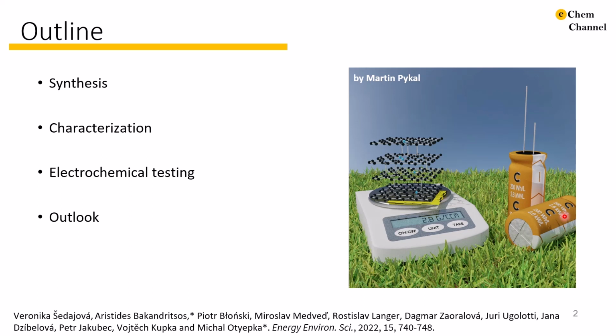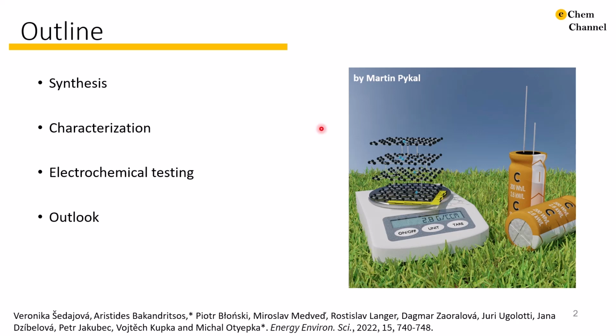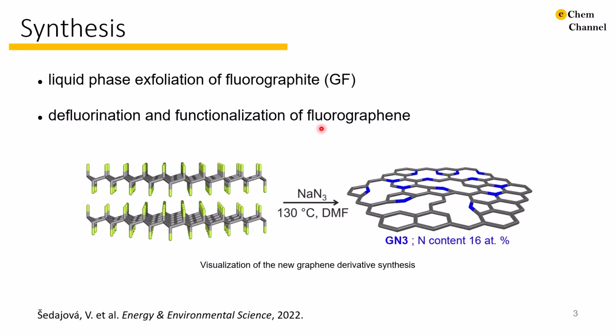First, I would like to show you the synthesis process, followed by the characterization of this novel material, and finally the electrochemical testing and benchmarking. Our novel material is synthesized via a wet chemistry approach. We exfoliated the fluorographite, which is used industrially as a lubricant, therefore it is a widely available precursor, in organic liquid